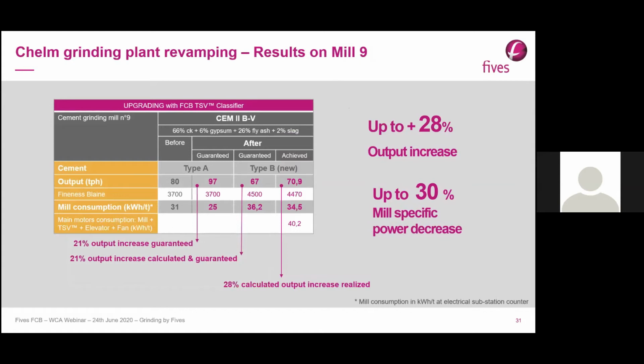Staying in this plant in Poland, Chelm, this is an example of the capacity increase achieved by installing the TSV. In fact, guaranteed outputs were calculated based on our FCB index grindability test, and with these two figures, first at 3,700 Blaine, the guaranteed capacity increase was 97 ton per hour instead of 80 ton before. It means a capacity increase of 21%.